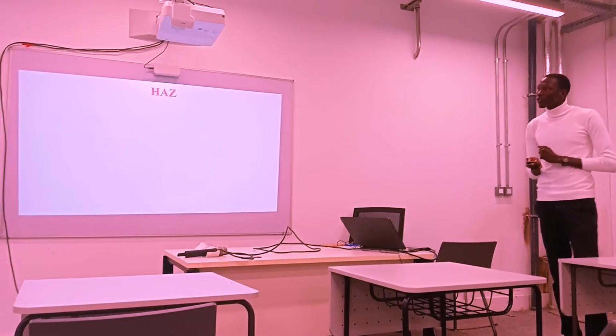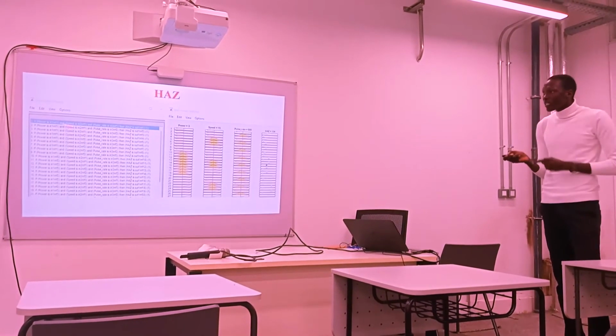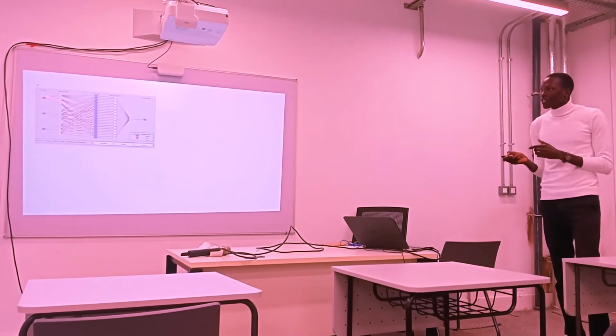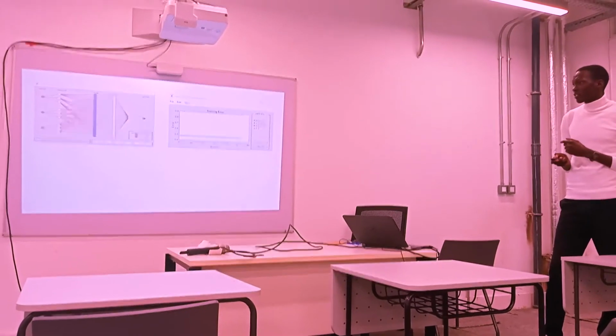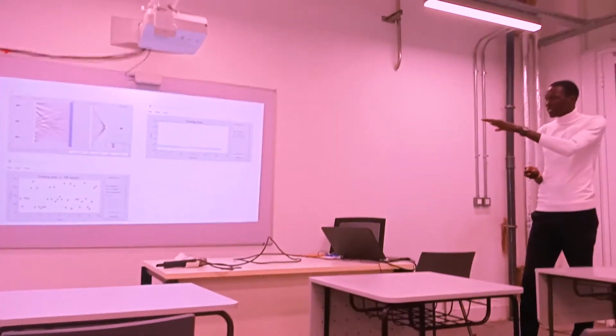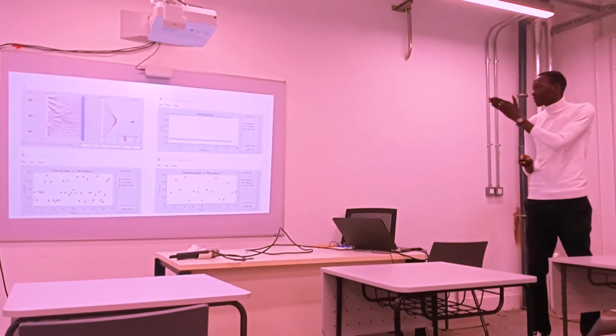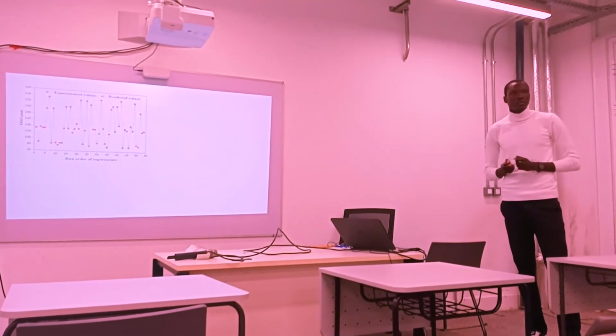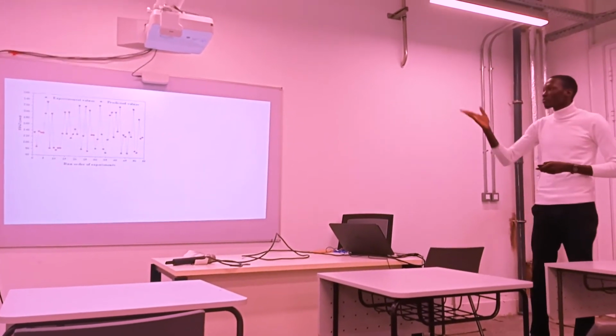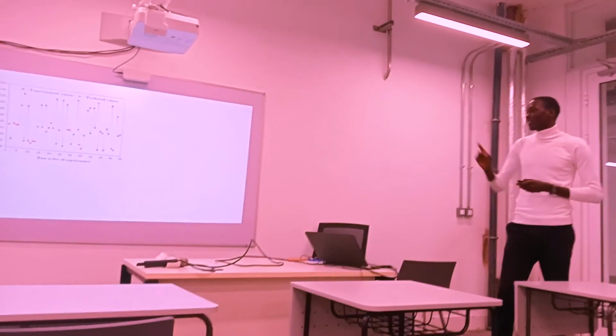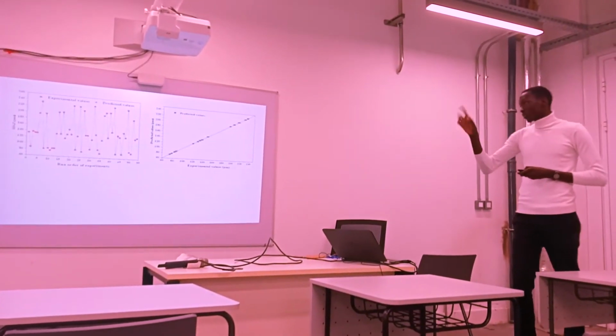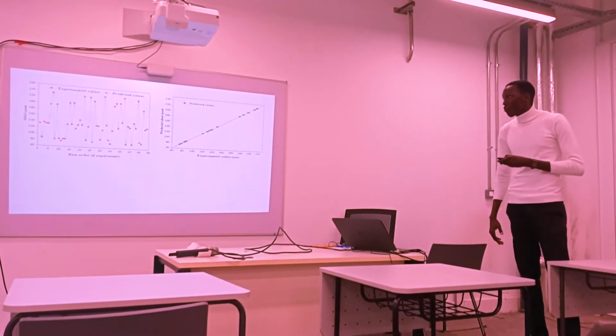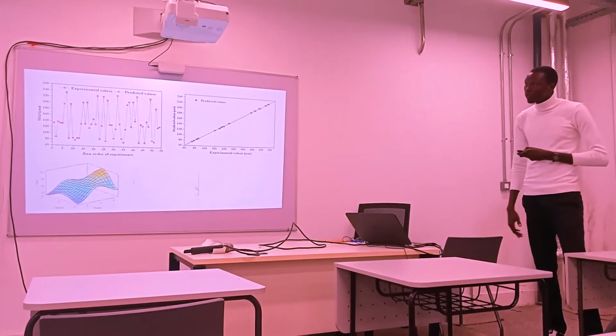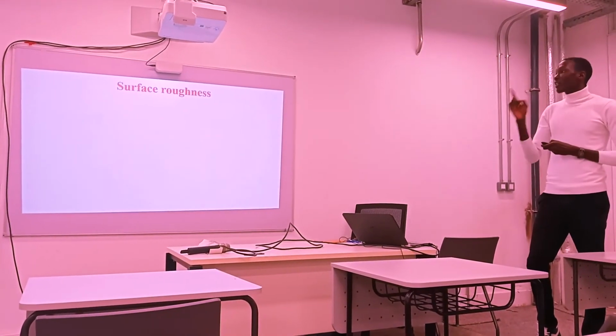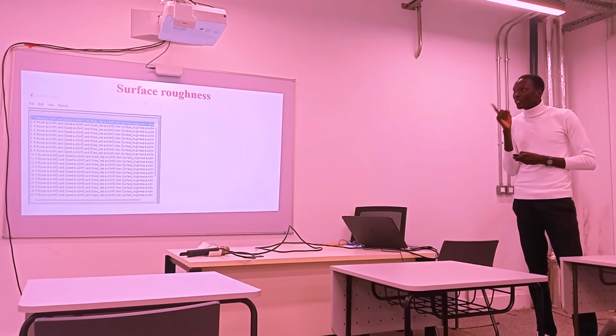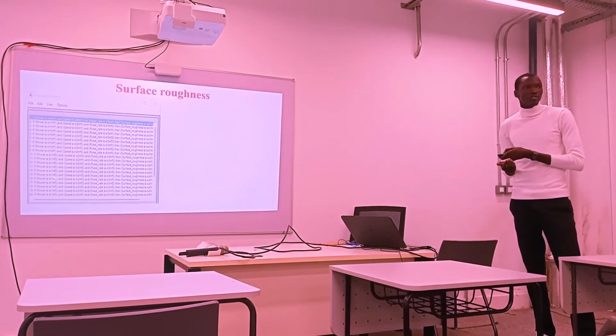We did the same thing for heat affected zone. The rules in the rule editor, in the rule viewer, the structure of the model, the training error, and the comparison of the training data and the predicted values, and the checking data and the predicted values. Then we compared the experimental values and the predicted values. Still very, very close. And then the same plot, the line of best fit crosses all the values, which indicates high accuracy of the model. Then the last one, the surface roughness. We did the same thing. The rules, the 27 rules in the rule editor.